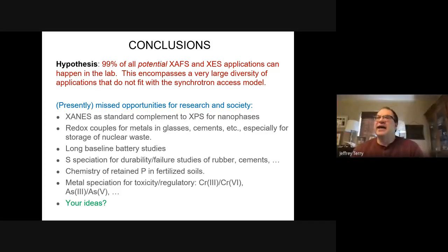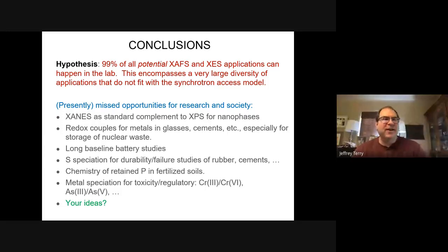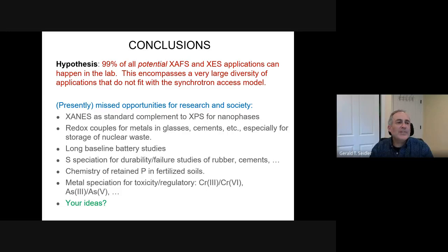Sure. The reason I ask is two of the elements that I find the absolute most difficult to study are magnesium and aluminum. Just an awkward energy range to cover. Yeah, we've gotten that question. I've gotten that question a lot. Silicon also people ask about. So there are high quality crystals of quartz or other large d-spacing materials that if you could curve them, you could use in the same way. It's not something we've pursued yet.